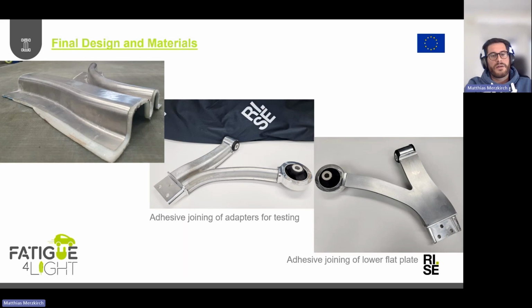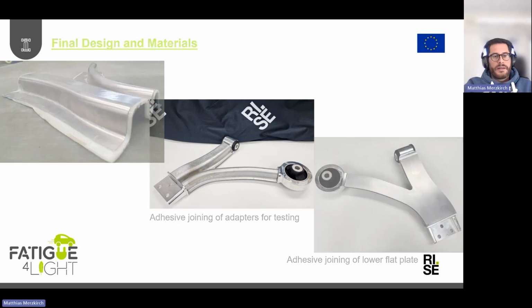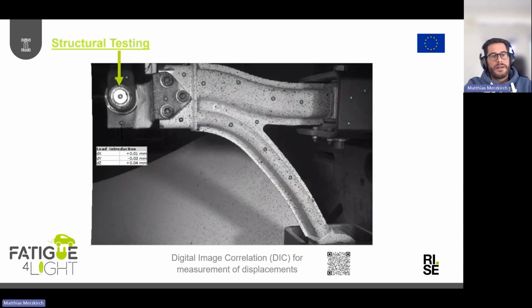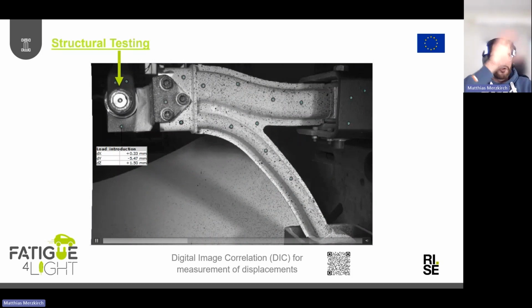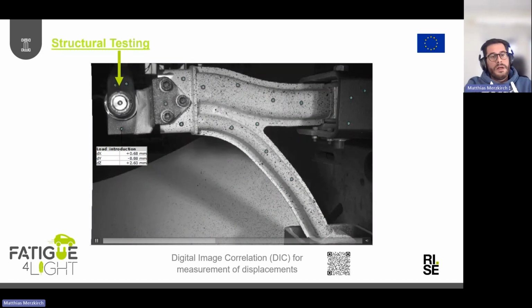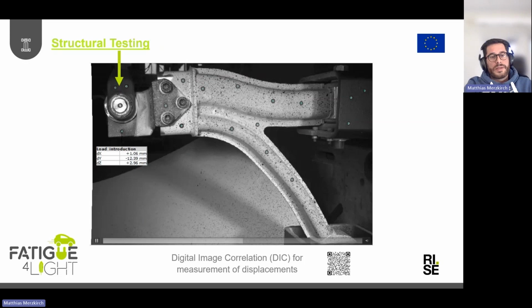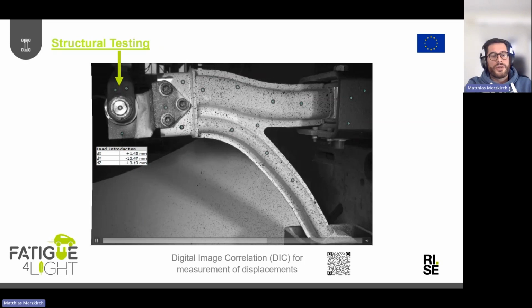So we have a 3D metal shape, three-dimensional shaped hybrid material, and a flat laminate glued on the bottom. And now it's testing time. So what we did here is a comparable test as Michele showed earlier. The load introduction was the same, just the orientation was a little bit different. So coming here from top, and it's quasi-static testing, and you see the structure here.